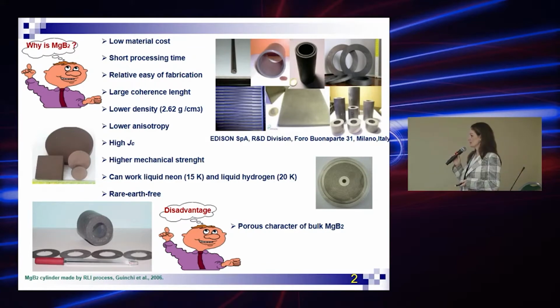In bulk MgB2, the grain boundaries don't form a strong barrier to current flow, and the grain boundaries support the supercurrents and don't show any weak link behavior like in cuprates. And there is higher mechanical strength. The ceramic nature of rare earth barium cuprates causes brittleness and low mechanical strength, but its counterpart MgB2 presents easy fabrication and large dimensions of different types of bulk superconductors like these images. MgB2 can work in liquid neon and liquid hydrogen, and it is a rare earth free material.